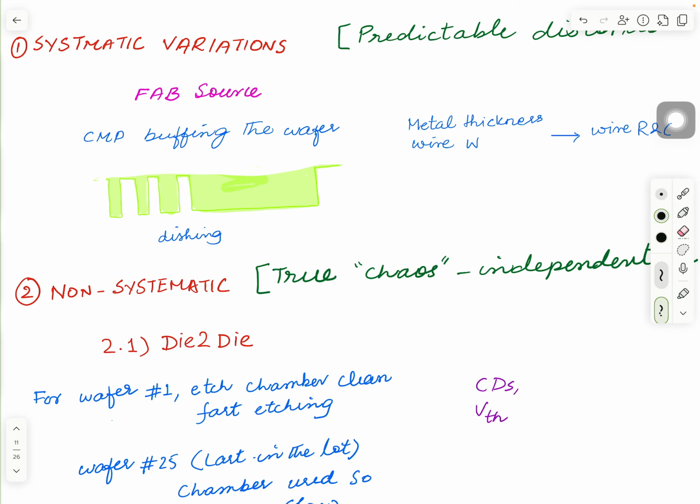When there is a large metal, it might create this dishing type of thing. So you can see here it's fine, smaller metal together, but here you have an area of long, wider metal, and it took more. Now these things, based on the layout, how close or far these are, during the extraction, the effect of some of these can be turned into resistance and capacitance variations.